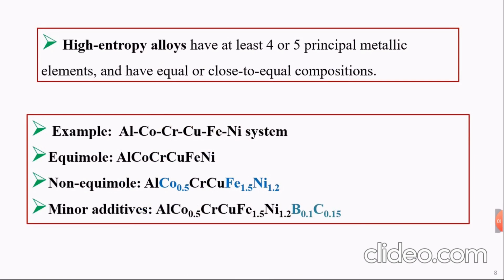Therefore, simply you can say high entropy alloys are alloys that have at least 4 or 5 principal metallic elements, and they can have equal or near equal compositions. For example, we have equimolar aluminum, cobalt, chromium, copper, iron, nickel, and we have non-equimolar, as you see. We can have minor additives in high entropy alloys, like carbon and boron, but you have to be careful. The minor additives should be controlled, because if they increase more than required, they will make the system not stable, and you will not have the high entropy alloys you desire with solid solutions. You can have intermetallics, so we have to pay attention.